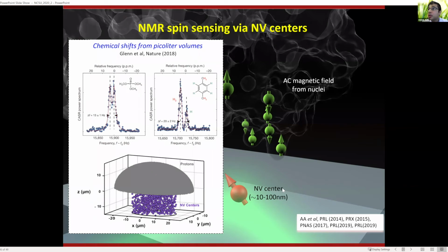The main advantage is it allows you to make NMR sensors at a length scale that's inaccessible from current NMR. And that's because the NMR detection is done with light. So you can really localize the NMR detection to either a surface or an interface, or generally to a volume, which is between tens of nanometers to, in this case, about 20, 30 microns in size.